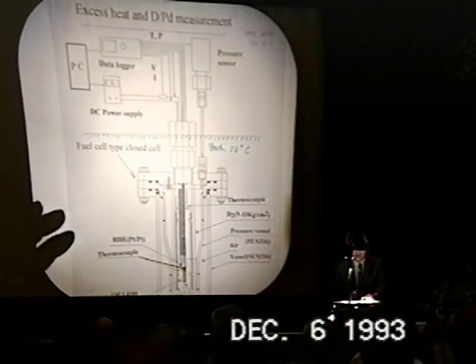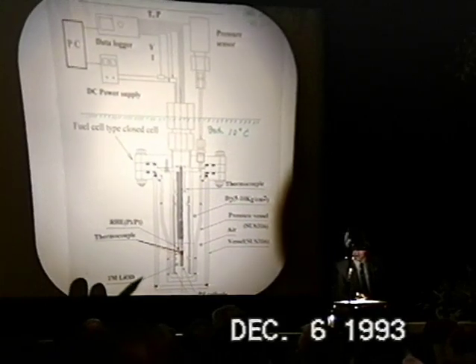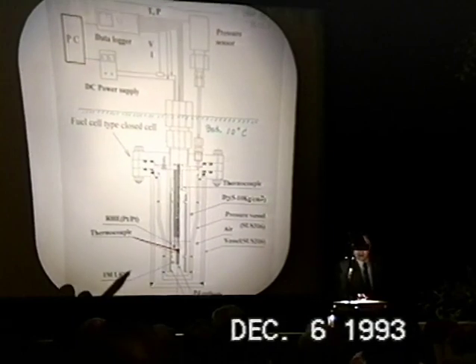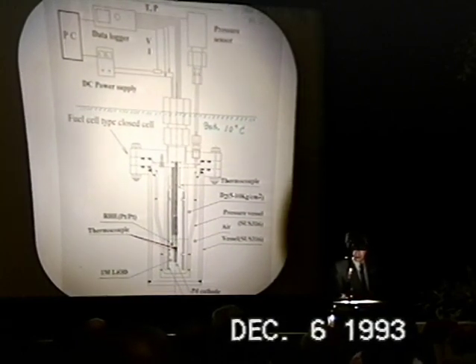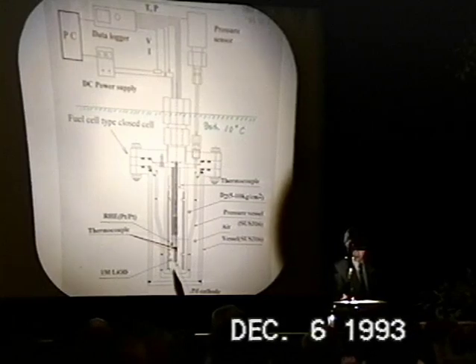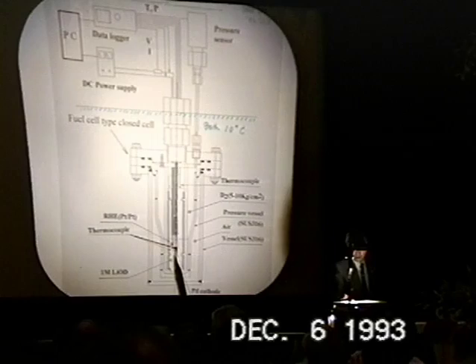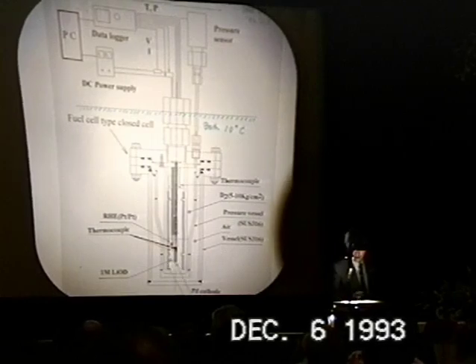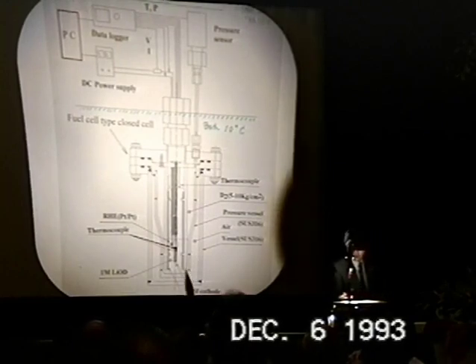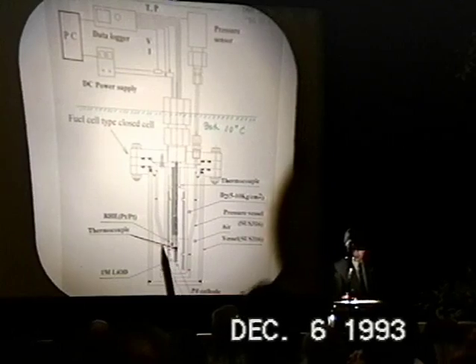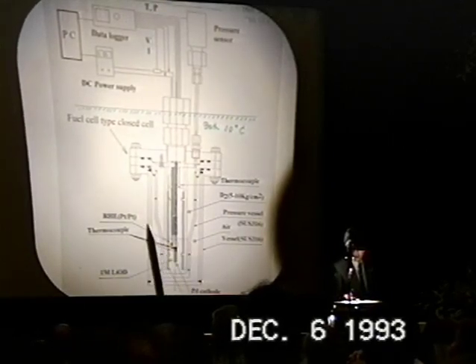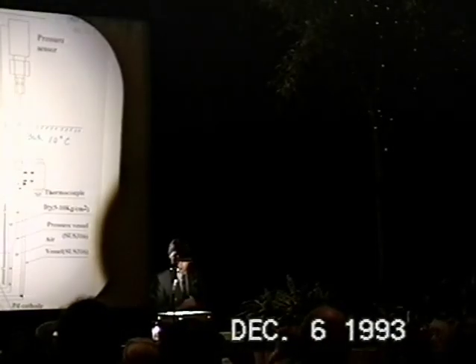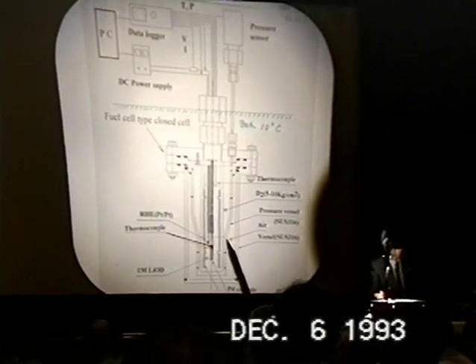So the actual system to measure the excess heat in D2O or PdD is described here by this block diagram. The essential point in our calorimetry is that we are measuring the temperature in the palladium cathode by inserting a thermocouple into the top portion of the cathode. And we have two vessels actually. One inner vessel which contains electrolyte, and then the outer vessel to have good heat insulation by the action of air in between the two vessels.